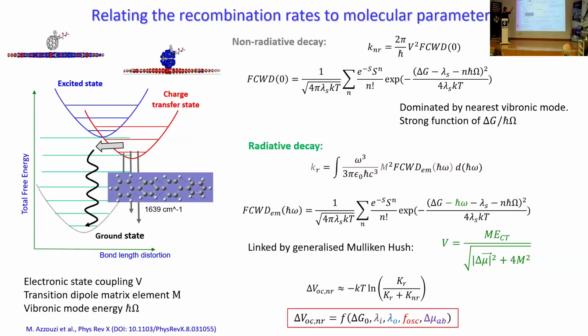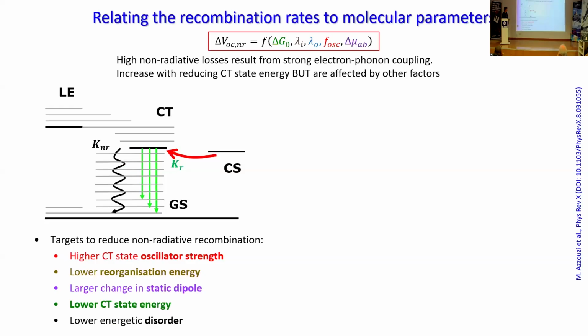However, when we have a theoretical description, you can work it out, and then you can see what your losses are a function of. And they don't depend only on the energy of these modes, but also on other factors. The coupling to those modes is represented by the reorganization energy here. But there are other things that matter as well, like the brightness of the state, the dipole moments, the energy of the state, and so on.